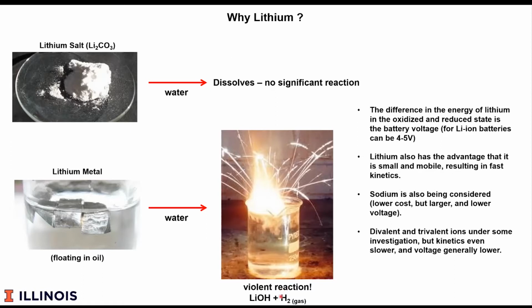It also liberates an incredible amount of heat, which of course immediately ignites the hydrogen gas with the surrounding air, yielding the flames that you see here. However, in its oxidized form, lithium salt simply dissolves in water with a very, very small exo- or endotherm of solvation, depending on the details of the lithium salt. And so it is really the energy difference of the lithium in these two states that determines the overall energy of the battery. And remember, it's not only the number of lithium atoms or ions, but also the voltage difference.